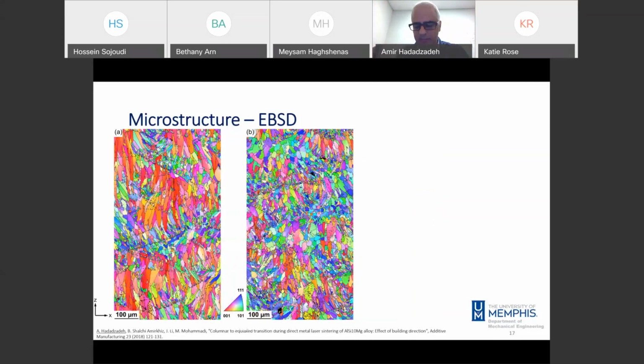Then I conducted EBSD, the electron backscatter diffraction. In electron backscatter diffraction, now we can study the grains. And in the context of additive manufacturing of metallic materials, there is a difference between the cell structure and grain structure. First of all, with EBSD, we can study both the grain morphology and also the orientation of the grains, or micro texture. The other feature here is the scale bar, the scale of the structure. So 100 micron. In the previous slide, the scale bar was 5 micron, and here it is 100 micron. So there is a change in the length scale when we are studying cell structure and grain structure.